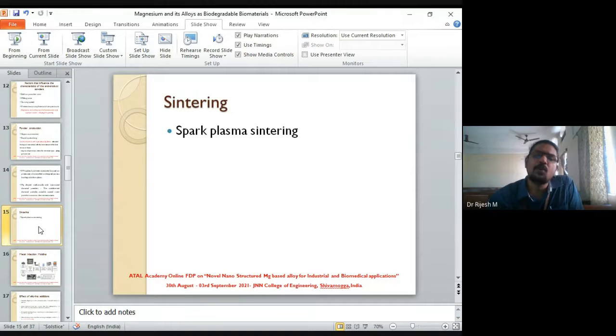Now the diffused particle will tend to grow, taking up all those porosities. Sintering temperature and sintering time again are chosen in such a way that you get the porosity that you want. Otherwise, what happens? Sintering helps in densification. These particles grow and consume all those voids and porosities. So if you want them interconnected in the same fashion that we have designed, we should always make sure that the growth is not that high, because we wanted nanostructures. So we go for a very specific sintering process called spark plasma sintering, which is concentrated only on certain particles and not throughout the specimen. So that's what is called spark plasma sintering.